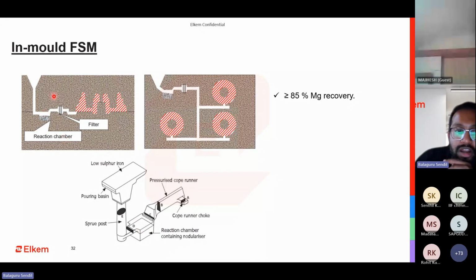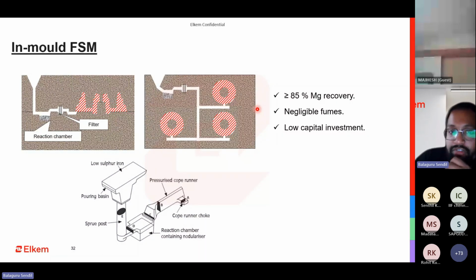Interesting point here is that you don't need to have a lot of fancy deslagging setup here, because the FSM that you use has to be of correct size and correct shape and correct chemistry. If you are not using that, then it becomes a headache. You will end up getting a lot of slag, draws, all these issues. So you don't have any fumes in this process because it is inside the mold, and it doesn't require a lot of capital investment. You don't need to invest in a ladle, you don't need to invest in training people, and it has very minimal environmental impact because the fume generation is very less.